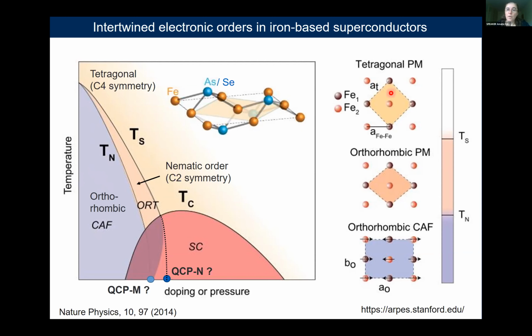So here is the representation of the unit cell at high temperature. You have the tetragonal unit cell where a and b are equal, but as you enter the structural transition, a and b become non-equal, so you break the rotational symmetry of the system, and at low temperature, the magnetic spins with a very small moment can order in a collinear antiferromagnetic state where you have ferromagnetic chains antiferromagnetically aligned with each other.